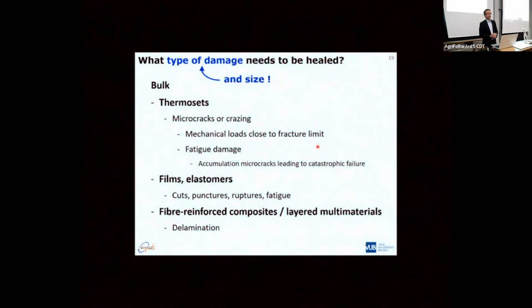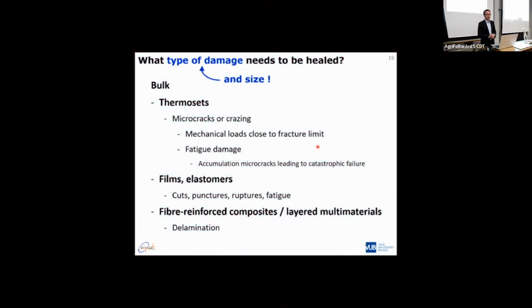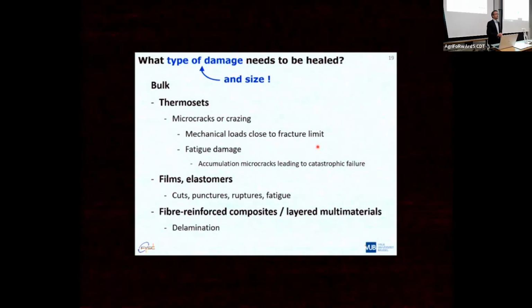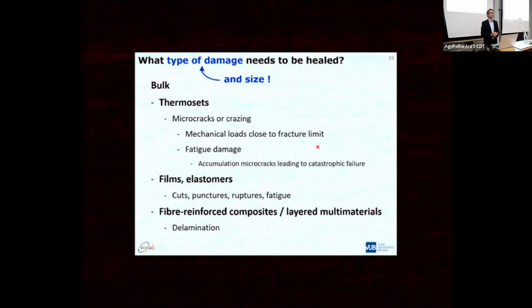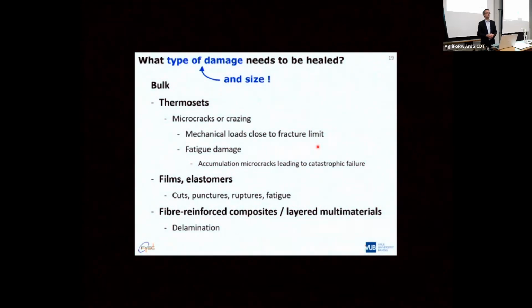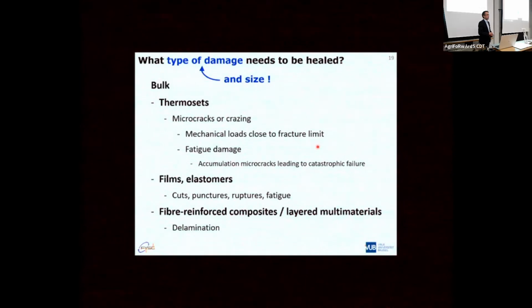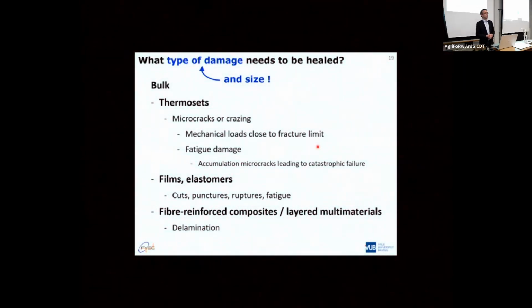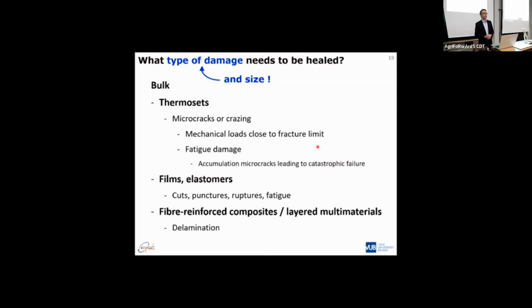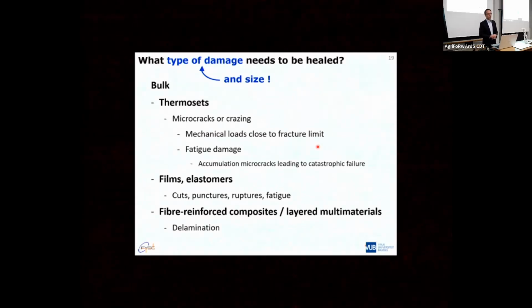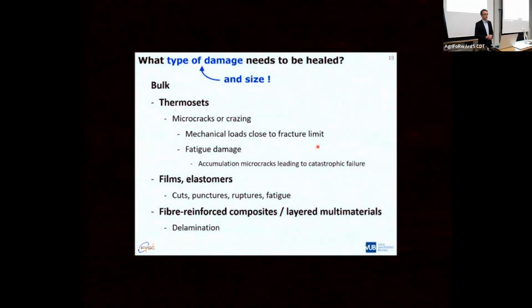So you can induce these by mechanical loads that are close to the fracture limit, or by bending it up to close to its bending fracture limits. But you need to realize that when you do this on samples that you made yourself in the lab, typically when you do fracture tests, you do something like 10 to get a more or less relevant statistical average out of these measurements. And when you try to, for example, load a sample up to 80% of its average fracture stress, it is quite likely that quite some of your samples will fail during this test. Yeah? So you are trying to induce a limited amount of damage, but in reality, you might fracture quite some of the samples that you are trying to create damage in.